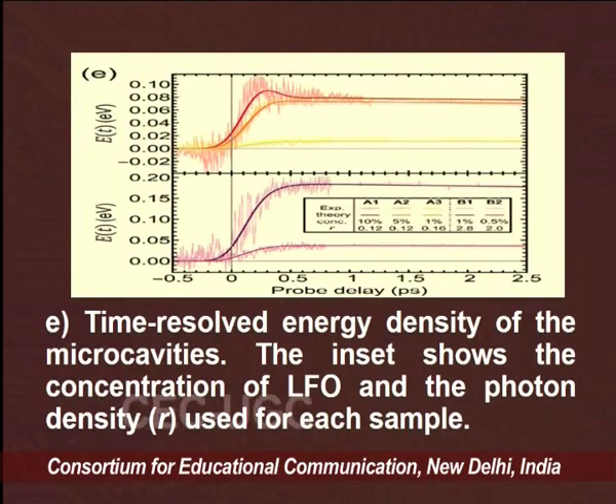In all microcavities, one observes a fast rise of the signal followed by a small decay. So, fast rise and small decay represent fast charging and small discharging. So, the time-resolved energy density of the microcavities shows the concentration of LFO and the photon density, defined by R, used for each sample. In all microcavities, one observed the fast rise of the signal followed by the slow decay, by analyzing the data taking into account the instrumental response function.